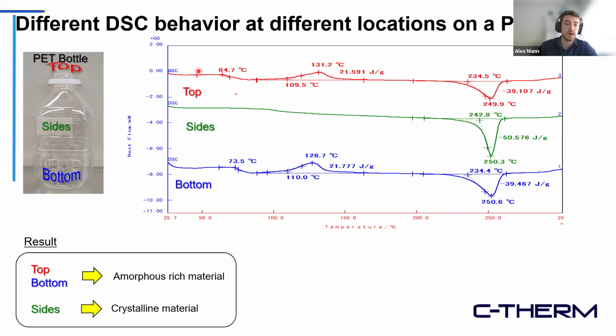So what we can see here is the top. We have a nice glass transition, which is shown by the shift in the baseline. Then we have an exothermic event, which happens immediately after. This is actually the glass transition, followed by the cold crystallization, where our polymers go from amorphous or random, no specific orientation, back to a nice crystalline ordered structure. Then after that, we can see we have a nice sharp melt, which is a characteristic of a crystalline material.